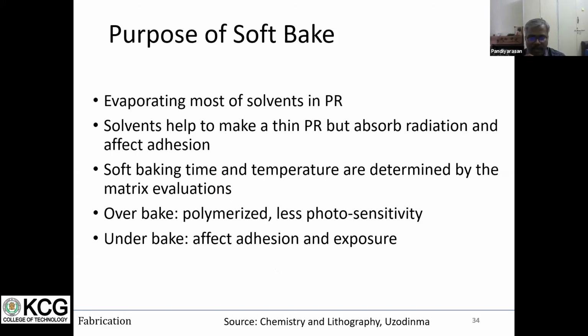The advantage of soft baking is that it evaporates the solvent from the polymer coated on the surface. For soft baking, we need to control the temperature. It differs based on the polymer. For example, if you take PMMA, polymethyl methacrylate, it goes up to 150 to 160 degrees. If you go beyond that, it is over baking. When you go for over baking, the resist gets polymerized and has less photosensitivity. Like if you take a scale and try to heat it, or bend it, you can see it is not in a transparent nature, right? That appearance will be present when you go for over baking.